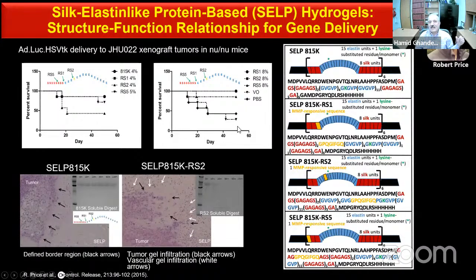And this demonstrates the influence of the structure of the polymer on the efficiency and activity of these types of adenoviral delivery systems. So the reason we believe for that is that if we excise the tumor and look at SELP815K, we have film formation, it doesn't quite degrade. That is also true when we did in vitro degradation studies. But when we incorporated the RS responsive sequence within 815K, we could see that the polymer is degrading in response to MMP, and basically the viruses are penetrating, and it gives us better activity.